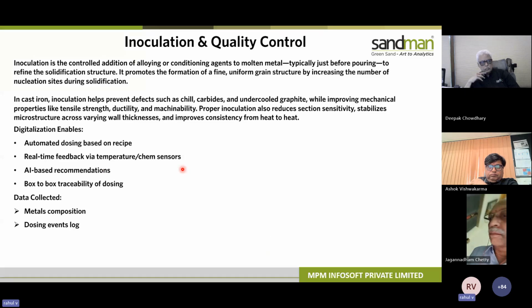Inoculation and quality control. Inoculation is the controlled addition of alloying or conditioning agents to the molten metal, typically just before pouring, to refine the solidification structure. It promotes the formation of a fine, uniform grain structure by increasing the number of nucleation sites during solidification. In cast iron, inoculation helps prevent defects such as chill, carbides, and undercooled graphite, while improving mechanical properties like tensile strength, ductility,